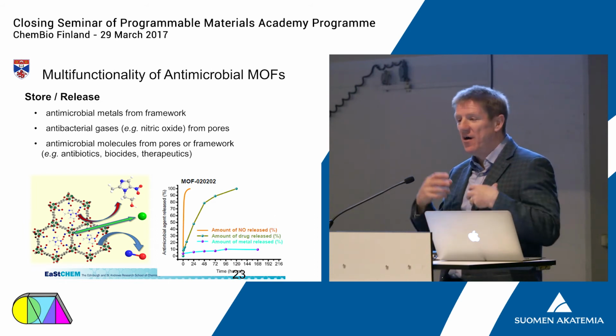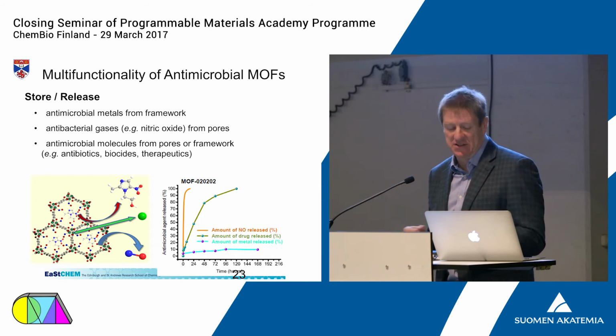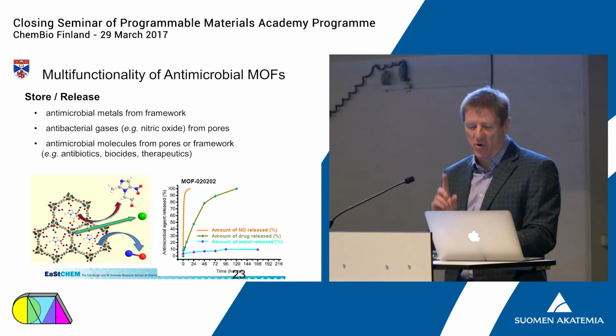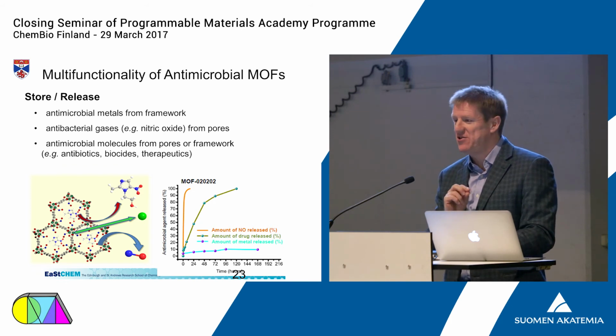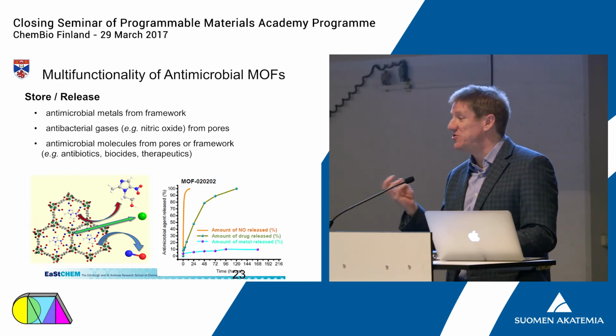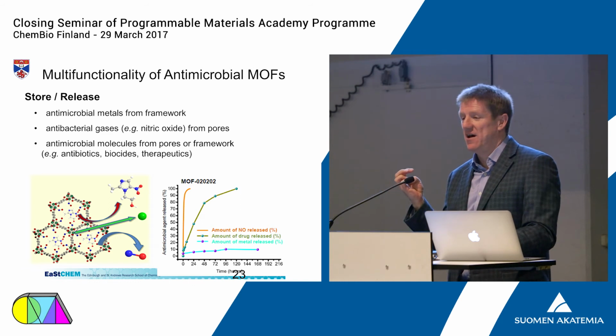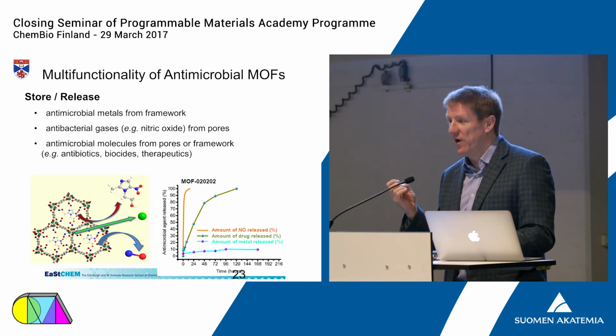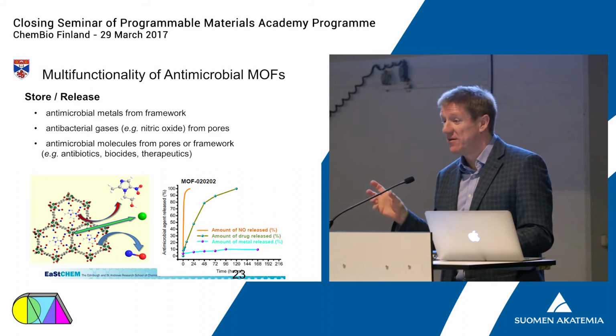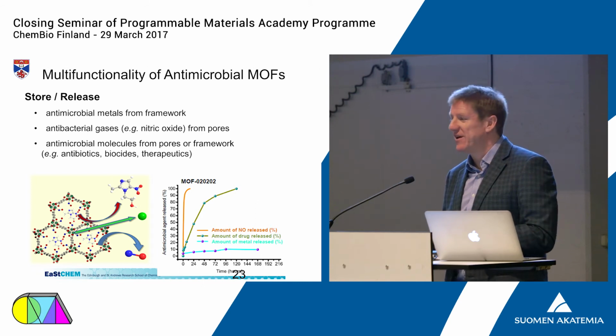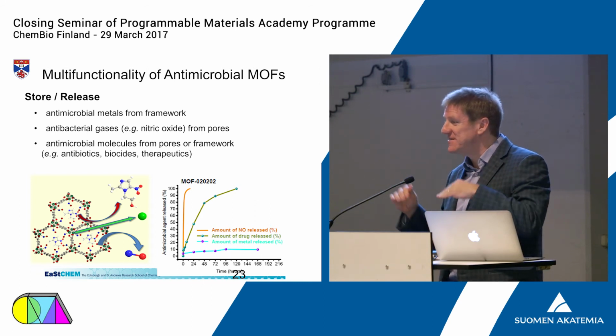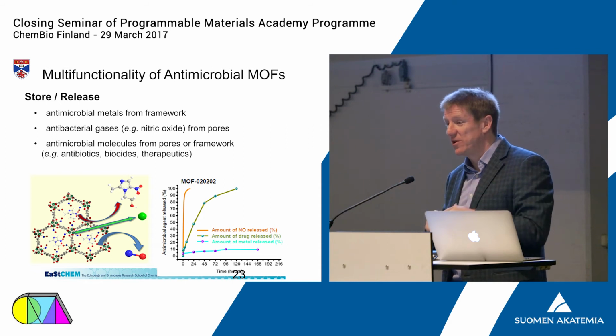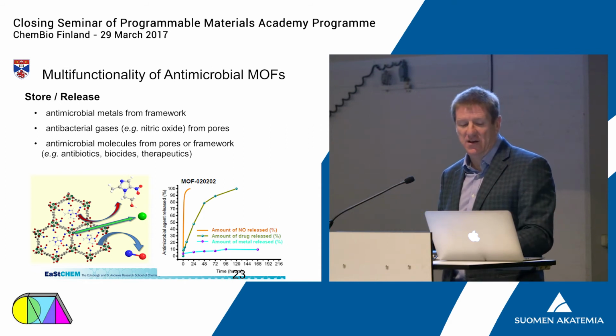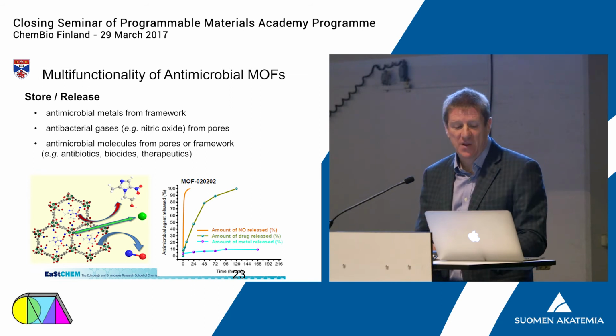So we get a multi-rate delivery of these, which is really important for one of our potential applications, which is long-term prevention of infections in urinary catheters, where these days they work for 3 or 4 days, where the real target is a month, right? 30 days. If we can produce something that delivers at different rates, perhaps we can elongate the effective killing. And how good are they?